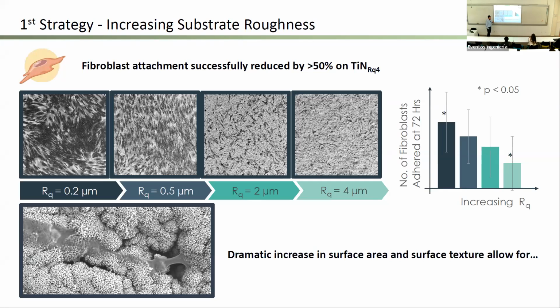And we have seen that after seeding the surfaces with dermal fibroblasts, increasing the roughness prior to deposition resulted in a drastic, about 50% decrease in fouling, which has been quite a positive result from that aspect. And over here, we're seeing a high magnification of this one here, and we're seeing that with this roughening, we're getting these clusters of coating with these star-shaped features with all these pits, and this was somewhat inhibiting the fibroblasts from growing and proliferating on the surface.